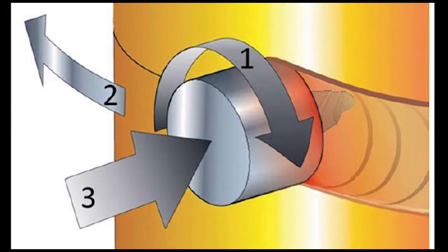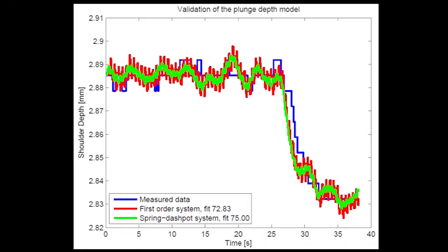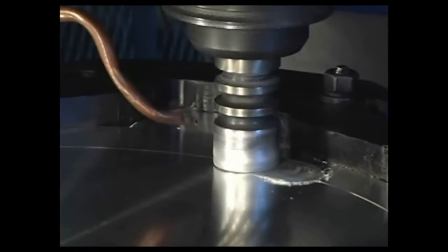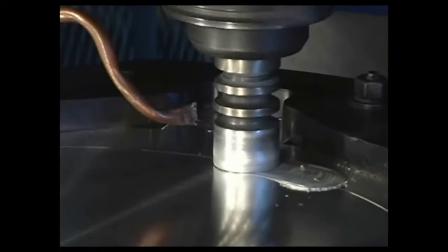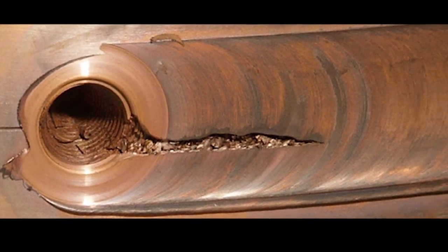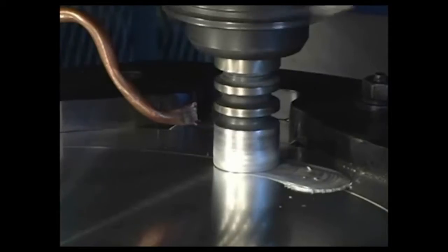To produce repetitive, high-quality welds, the process must be controlled to tight specifications. The control system maintains stir zone temperature and plunge depth. If the temperature of the weld is too hot or cold, it can produce weld imperfections that may lessen the effectiveness of the seal. This study includes details of a strategy to better adjust axial force and spindle rotation speed to produce the best quality seal.